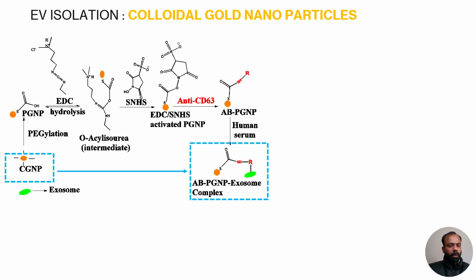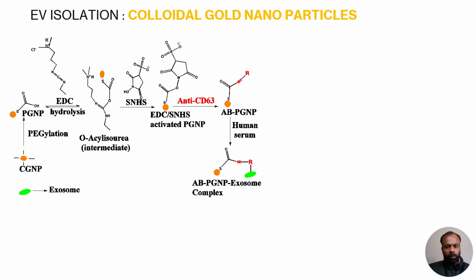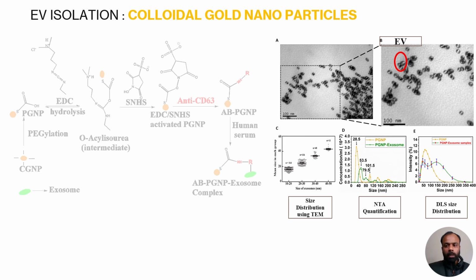The synthesized gold nanoparticles are functionalized with polyethylene glycol and treated with EDC and NHS to make them suitable for conjugation with anti-CD63 antibody. These nanoparticles are then incubated with serum to isolate the extracellular vesicles. They can be centrifuged and pelleted at the bottom of the tube. TEM image confirms the isolation of extracellular vesicles. DLS and NTA were also used for characterizing the isolated vesicles.